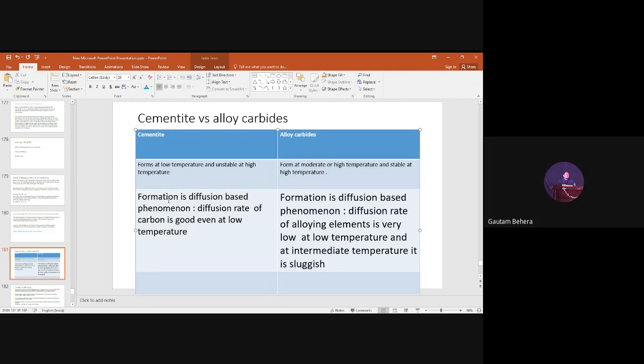For this statement, you can see that cementite formation is also diffusion based. Diffusion rate of carbon is good even at low temperature. Since the rate of diffusion is higher at low temperature for carbon, cementite easily forms. But in the case of alloying elements, the diffusion rate is very slow, so they do not diffuse much. If you go to a very high temperature, the diffusion rate will increase, then the alloy carbides will form. So this is the main reason behind the formation of alloy carbides at elevated temperature during tempering, which leads to an increase in the strength and hardness of the steel, right?